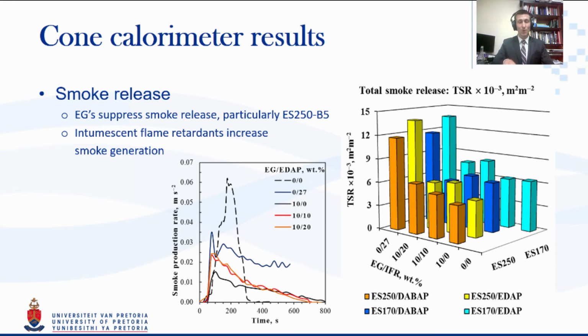So this was actually a bit of a best case scenario, because not only was it capable of suppressing that smoke quite substantially, but when we tested the materials in a binary system, although the organic materials do increase the smoke generation, in the binary systems it was still within a margin close to that of the original neat material. So that was quite a good result that we got.